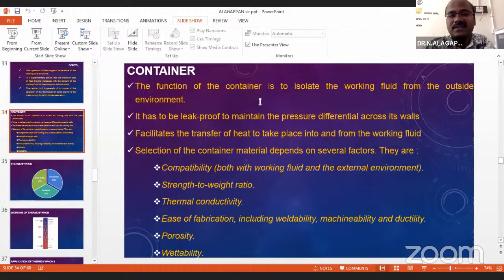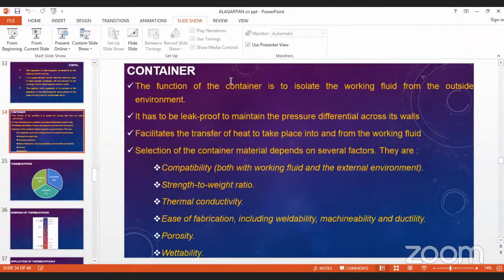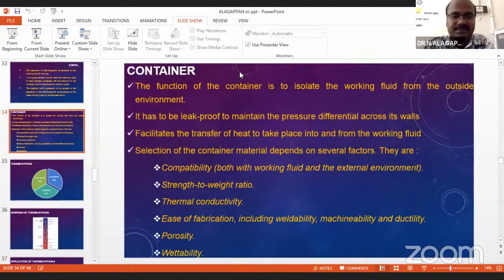So there is a lot of research gap in this area, container material. Here I am using three kinds of materials for my research work. First is copper. Then another two materials are 405 stainless steel, the grade of stainless steel I selected is 405, and 6063 aluminum. So these are the container materials I selected for my research, and I am also using five kinds of nanofluids. One is Fe3O4, and another one is cerium oxide, copper oxide, carbon nanotubes, and also TiO2, titanium dioxide. Next slide, sir.